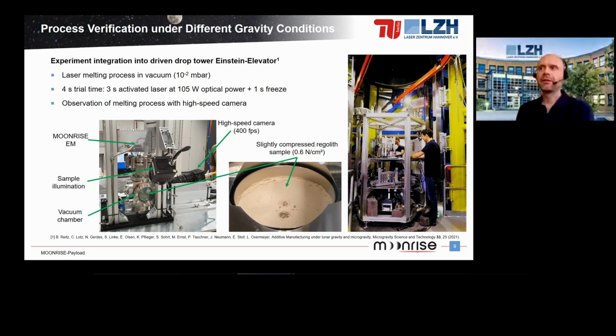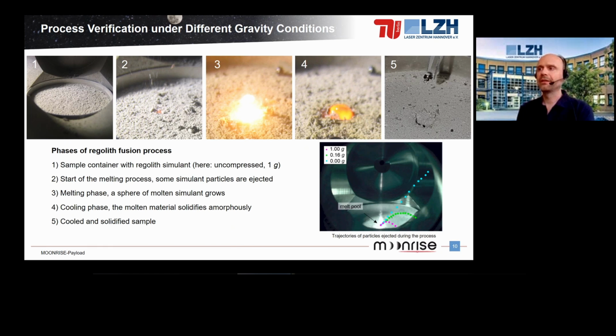The laser melting process was in vacuum again, and we also had a high-speed camera to observe the process. We had to slightly compress the regolith because of the low gravity conditions. So here you can see the process under 1G with uncompressed regolith. On picture 1 you see the sample container, on picture 2 the melting starts and some particles are ejected, on picture 3 there is a sphere of molten simulant, on picture 4 it's cooling down, and on picture 5 it's removed. And on the lower right you can see the different gravity conditions.